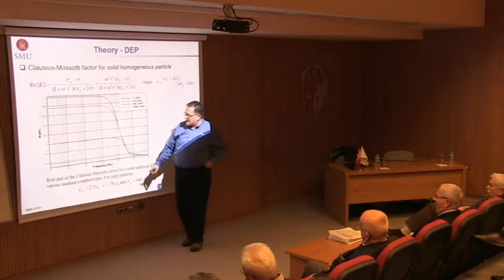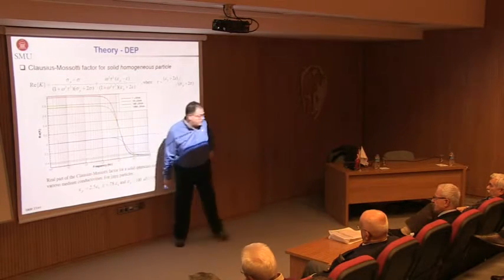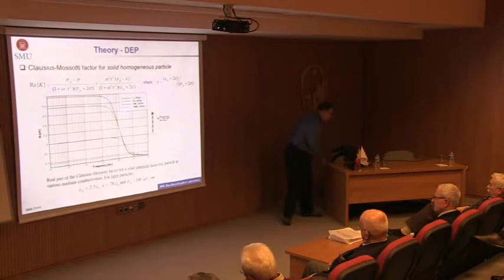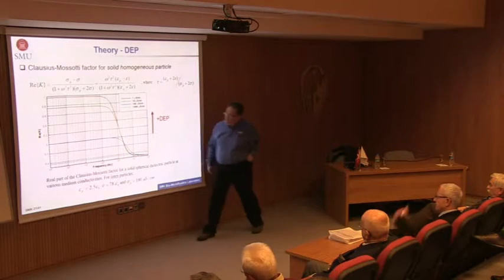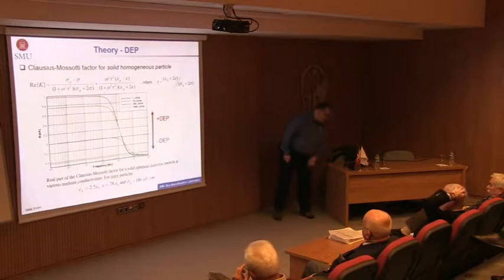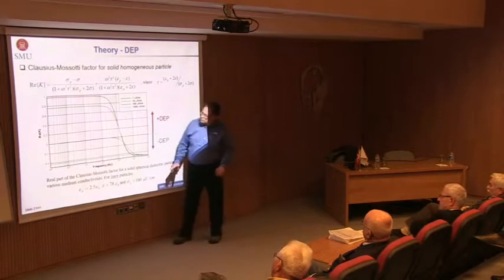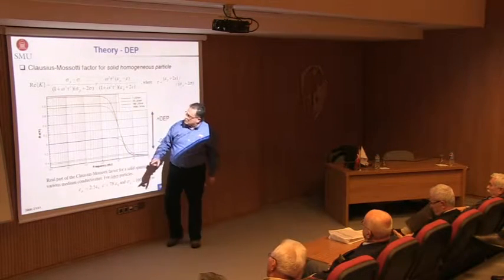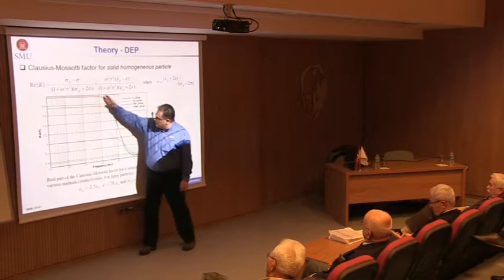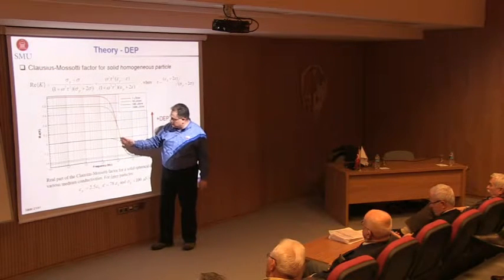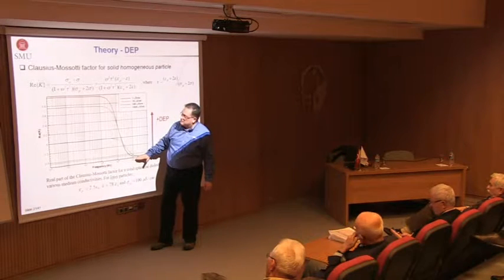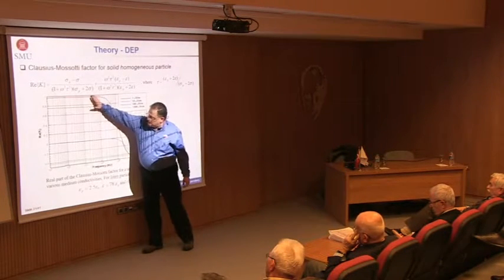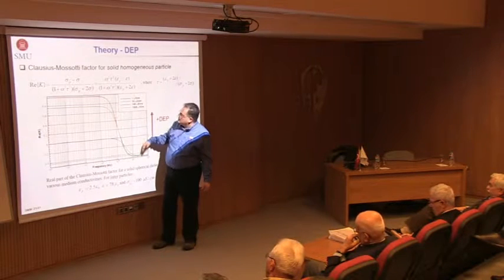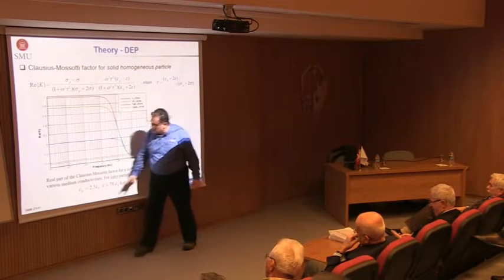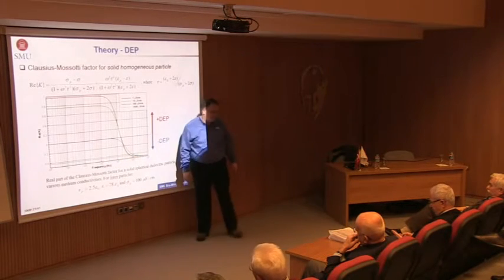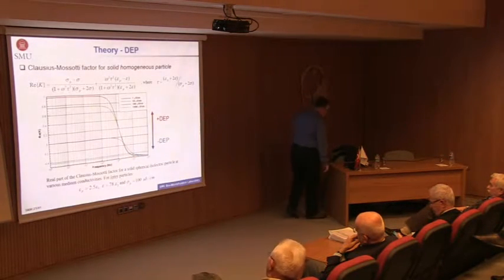like latex. And based on the frequency space, you may have so-called positive DEP if the Clausius-Mossotti factor is positive, or you will have a negative DEP if it is negative. And it's also noteworthy to realize that at lower conductivities, you can have a strong positive DEP, and then there's a crossover somewhere around here. This is a crossover frequency, then it becomes negative. So that's why positive DEP response and negative DEP response can be different. And in high conductivity fluids, you may only be ending up with negative DEP for, say, latex particles.